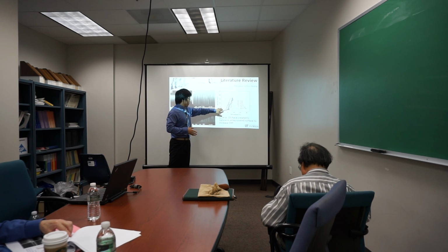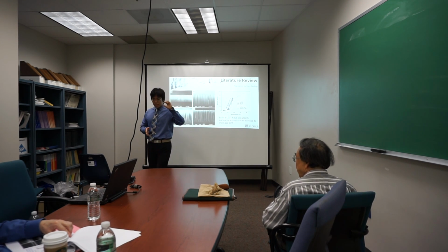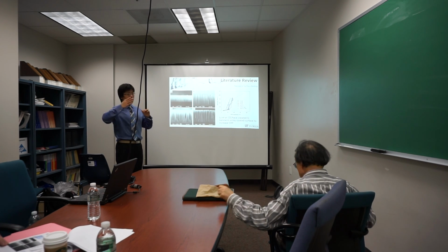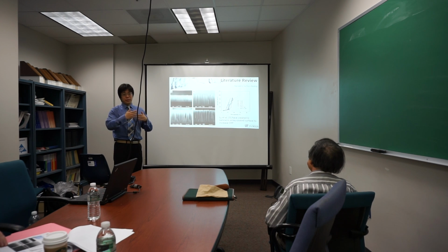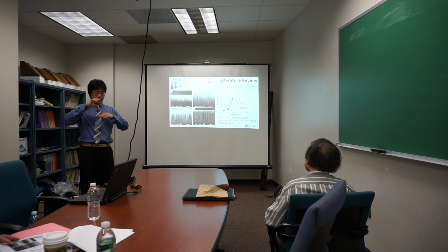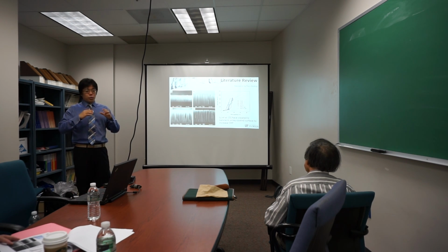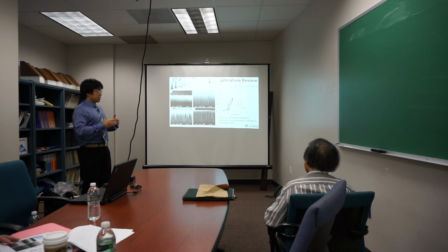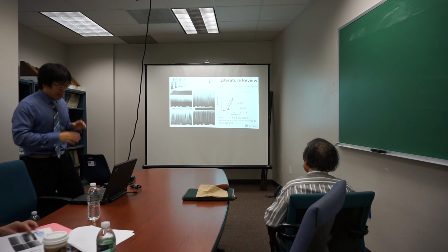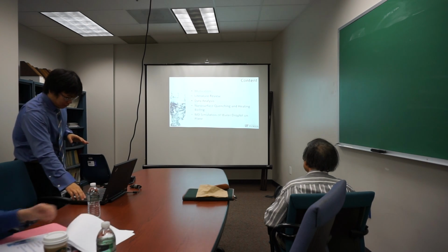But with different lengths, you will find the shorter length, like 16 microns, will do the best job. But when you have it longer, it doesn't actually improve, but actually decreases the efficiency. So all of the nanowires create a surface like a thermal barrier. When it is too long and too dense, they have a lot of vapor inside. They try to store the vapor inside and prevent the bubble from being created. So that actually functions like a thermal barrier. That's not something we want. That's bad. So based on all of these things, we try to do something different.